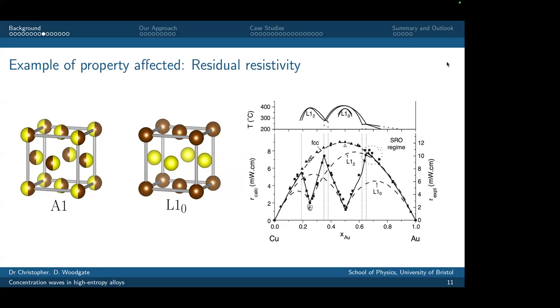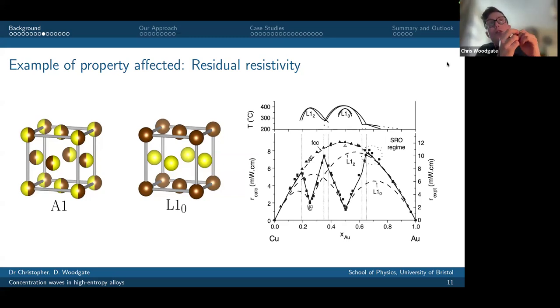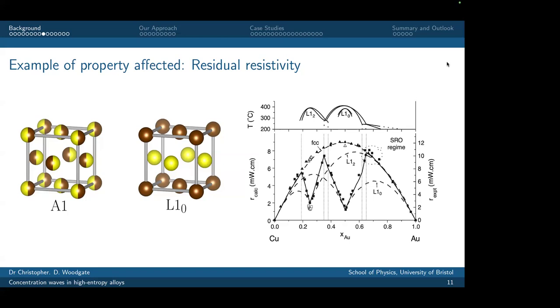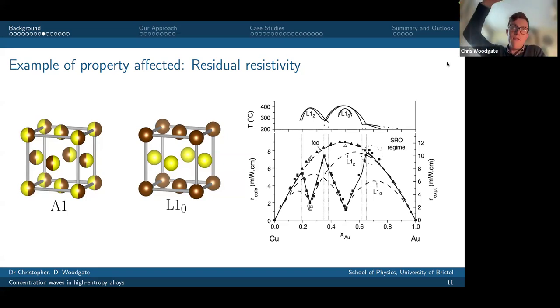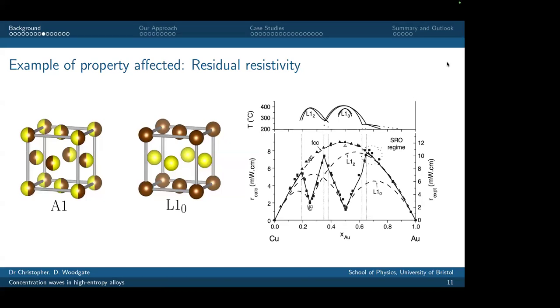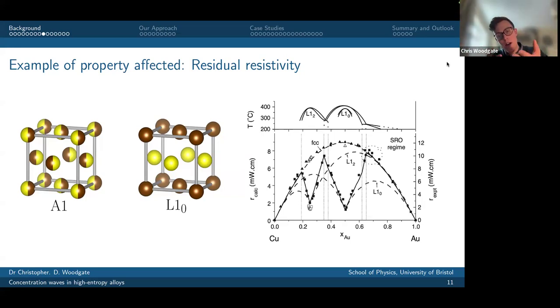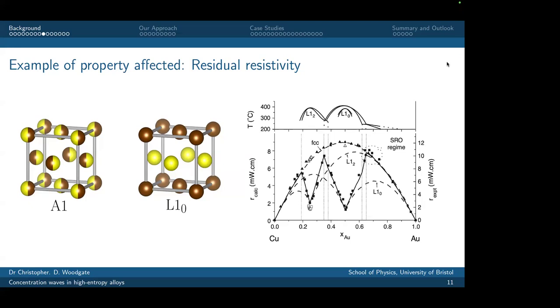I see you have some solid line, right? Above the solid line, and then below the melting temperature. Yeah, exactly. This is not my figure, this is a figure I pulled from an experimental paper. You imagine as you cool the material down from the liquid, you essentially have minimal short range order at very high temperatures, and then as you approach the transition, the short range order will grow until you reach the temperature at which the transition occurs, and then long range order begins to establish itself.